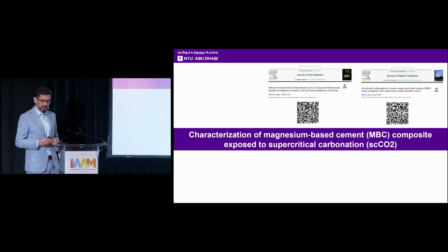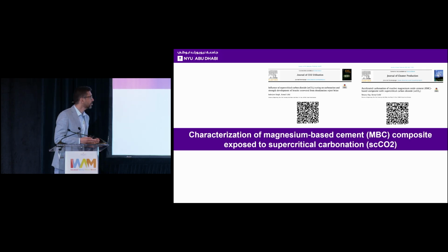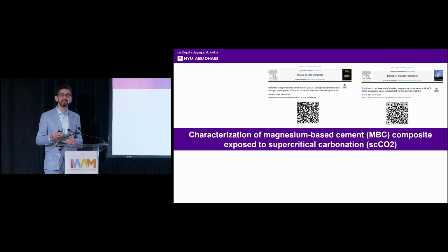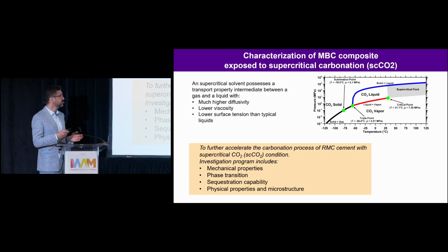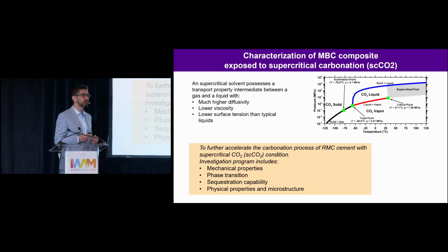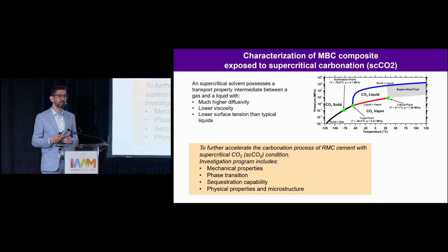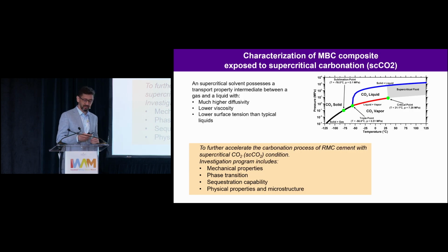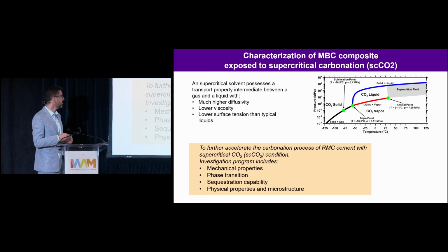So another project that I want to highlight is using supercritical CO2 to accelerate the carbonation process. As you are most likely familiar, supercritical CO2 has a low viscosity and can penetrate deeper and deeper into the materials. And what we need is just to increase the temperature to around 31 degrees Celsius, and the pressure to around 7.5 megapascal, and then see the phase transformation and CO2 sequestration capability in the matrix.